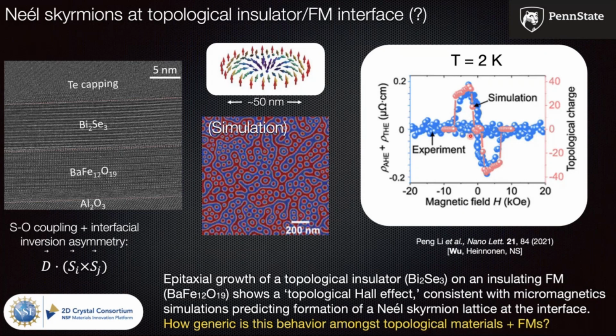Now, we do not have imaging. So, I can honestly say that there is a possibility that the transport may still be due to some funny artifacts. And the Würzburg group has talked about the kind of artifacts that can emerge, and so have we. But it's a very interesting idea. The idea is that you take barium hexaferrite, which is an insulating ferrimagnet, and you grow a topological insulator on top. So you can imagine, what if we now grow a quantum anomalous Hall insulator on this barium hexaferrite, right? That would be an interesting thing to explore. And we're certainly working on this.